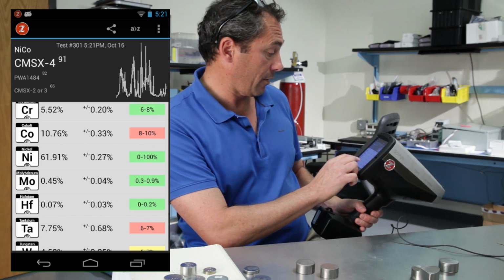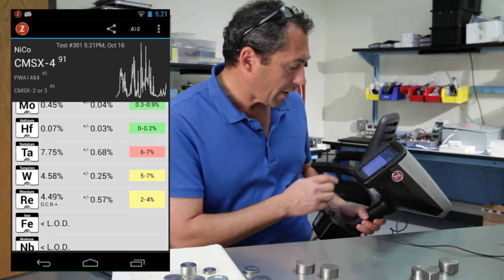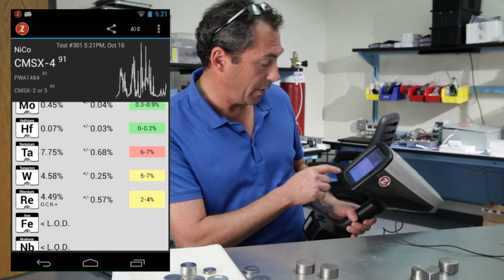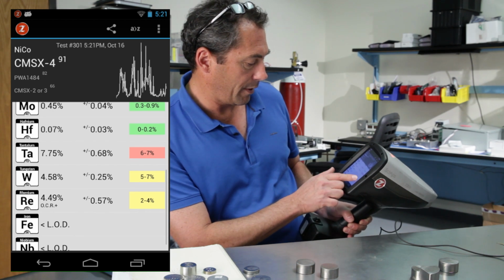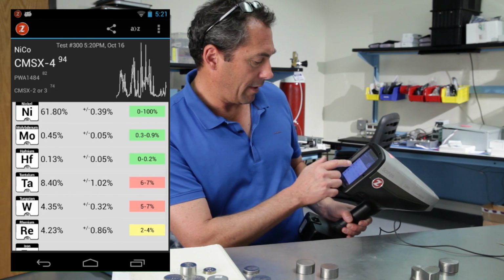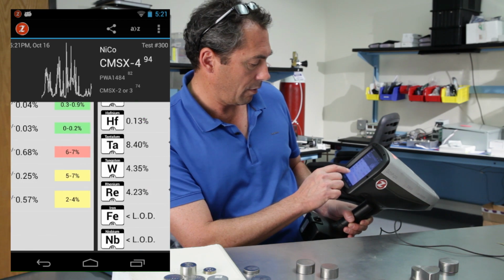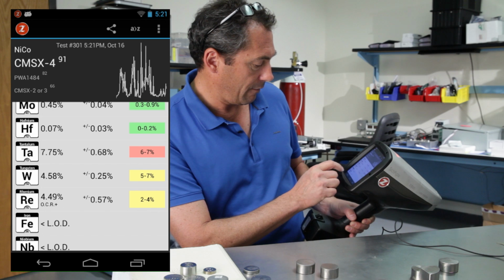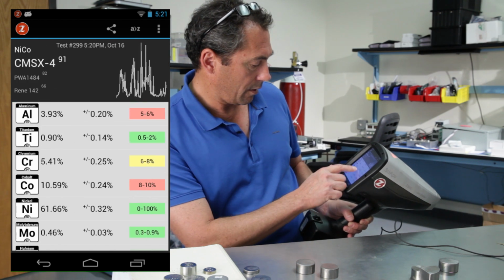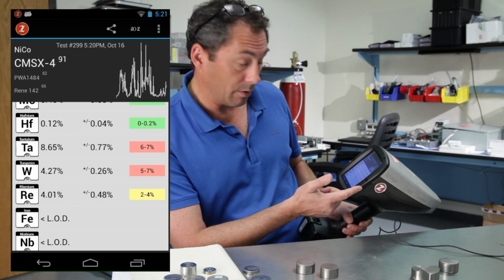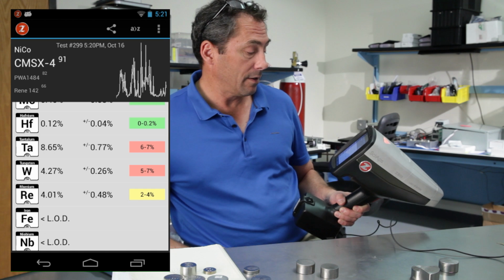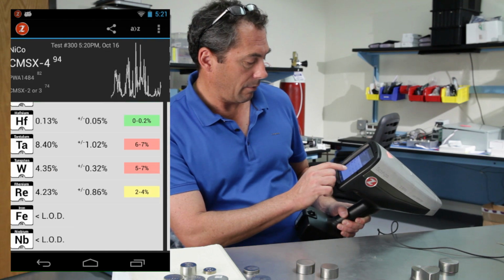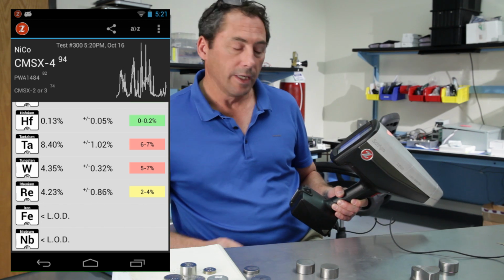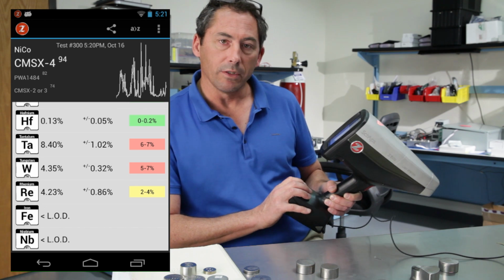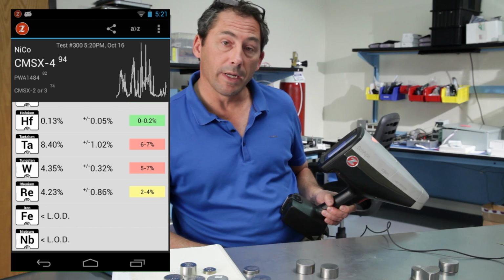And then the thing I like to point out about this is, let's scroll down a bit. Tantalum 7.7, tungsten 4.5, rhenium 4.5. That's 1 reading. Let's just focus on those 3. Tantalum 8.4, tungsten 4.3 versus, what was it before, 4.6. Very good. Rhenium was 4.5, 4.2. Then the 3rd test back. Tungsten 4.27, rhenium 4.0. So again, tungsten, tantalum, and rhenium are probably the hardest elements to measure with LIBS. And with the argon and the spectrometer and the laser, even those we can do with this. So we have customers testing the super alloys with our handheld LIBS, and it's working quite well for that.